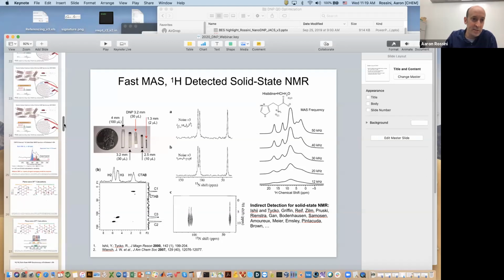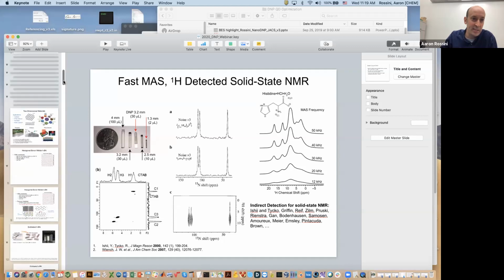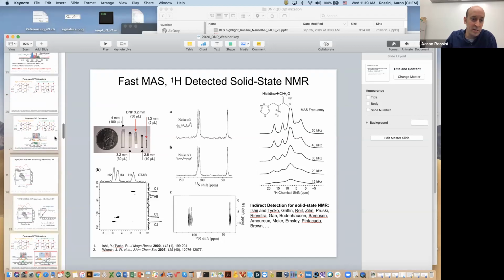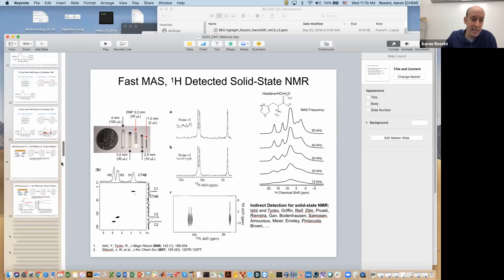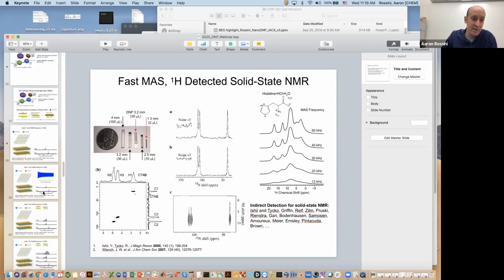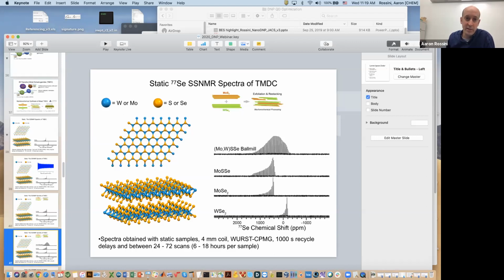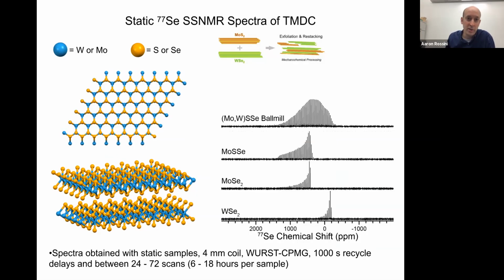We've tried a couple times to do some faster magic angle spinning experiments, using a 2.5 millimeter rotor to do 25 kilohertz MAS selenium experiments, and we still kind of fail to get reasonable magic angle spinning spectra. So I think the loss in the T2 maybe hurts you more than the reduction in the T1. How much is the loss in the T2? Well, we can't really see the signal under magic angle spinning. Under static, I'm under the impression we can maybe acquire echoes for, say, 10 or 20 milliseconds, but certainly not for seconds anymore.